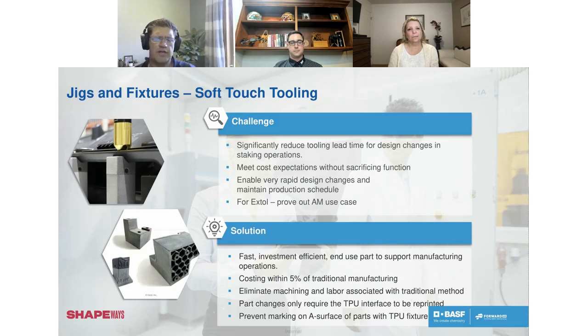So you can see that just the very end of that work holding device is a little bit different color, and that is the TPU. The TPU has been tested to not mar, not scratch. It'll protect Class A surfaces. There's a video floating around out there from my buddy Paul DeWise, who did a test of I think 100,000 cycles of pressing a Class A badge into a TPU holder, and kept shimming it to make it rub on the edge of the TPU and try to damage it. No damage to the badge whatsoever, other than he shimmed it far enough that a piece of the badge broke off. But no scratching whatsoever. So this material is able to hold Class A finishes. It's able to hold them in place.